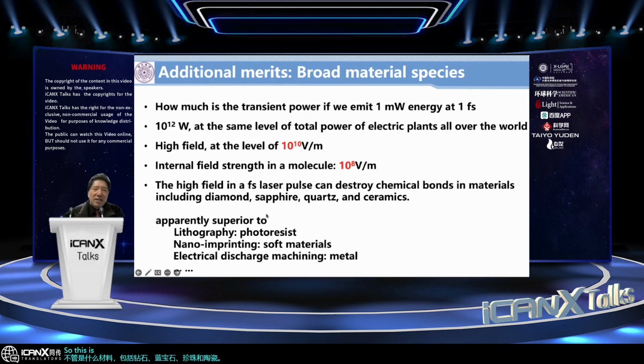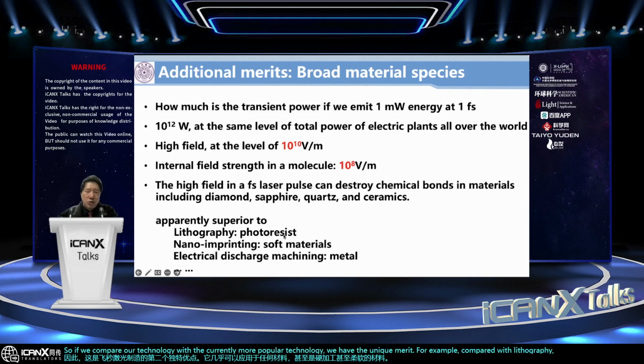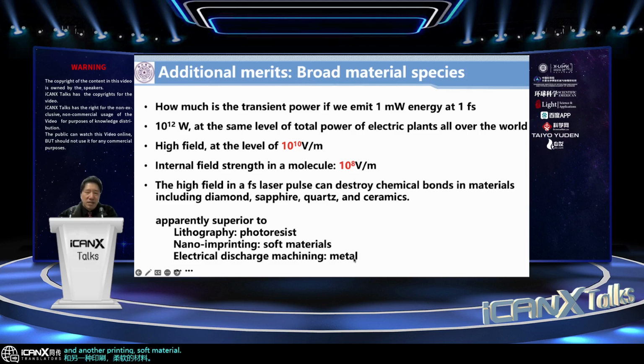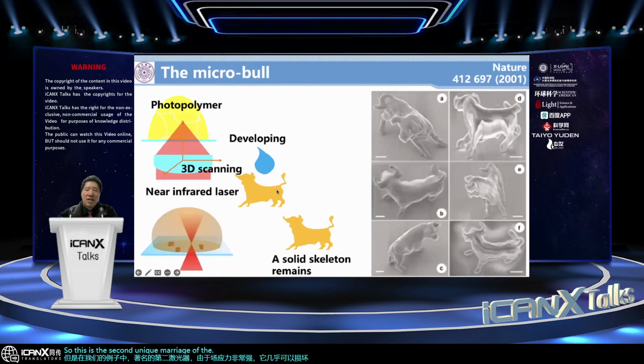So this is the second unique merit of the femtosecond laser fabrication. It could be applied to almost any materials, even if they are hard to process or soft. If we compare our technology with the currently more popular technologies, we have the unique merit. For example, lithography is applicable only to photoresist, and nanoimprinting is for soft material, and this needs a mold. But in our case, with the femtosecond laser, since the field strength is very strong, it can damage almost any materials.